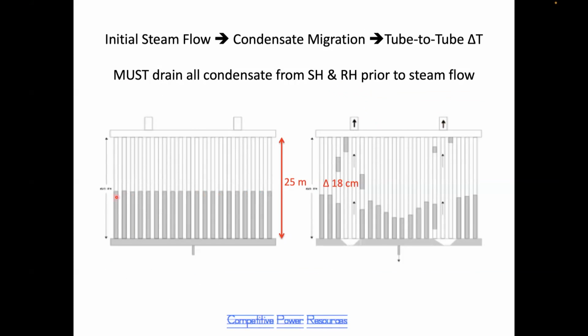This is a cartoon again of a harp where the water has been allowed to accumulate to this level. This harp's 25 meters tall. When steam flow begins, it passes first through tubes in line with these outlet nozzles. This cartoon is depicting that movement of steam up these few tubes moves the water upwards and on into the pipework downstream. The water in these other tubes away from the nozzle does not move immediately. And so this is the mechanism that drives it: when these tubes are full of water and the exhaust gas is coming through there at 550 degrees, the tubes themselves are at 550 degrees.